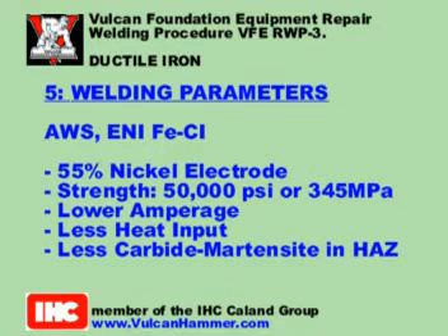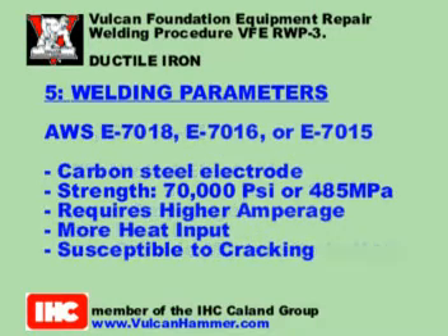Option 1. AWS ENiFeCl. This is a 55% nickel electrode having a weld strength of about 50,000 psi or 345 MPa tensile strength. It requires a lower amperage and less heat input. It melts at lower temperature than carbon steel electrodes, therefore, creates less carbide martensite in the HAZ.